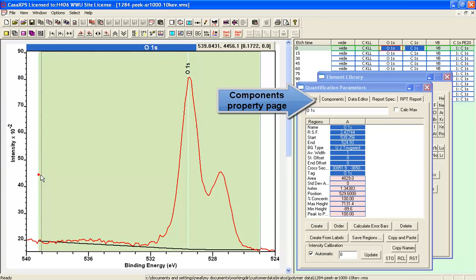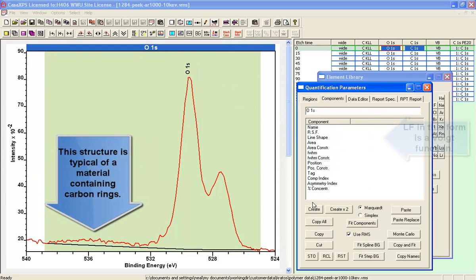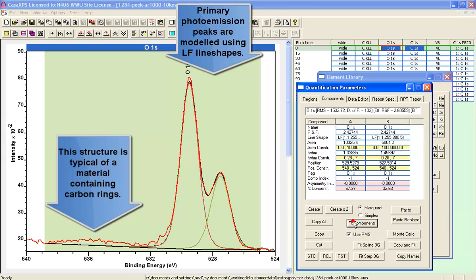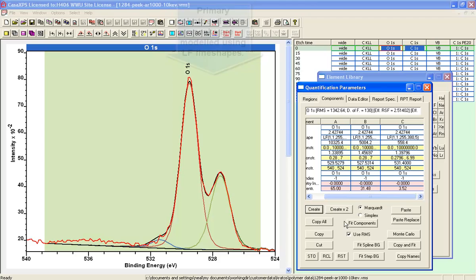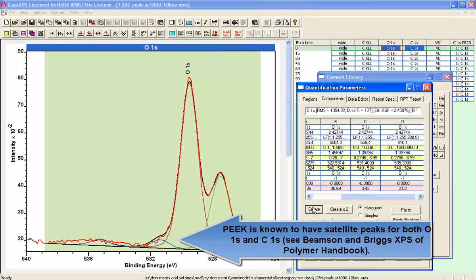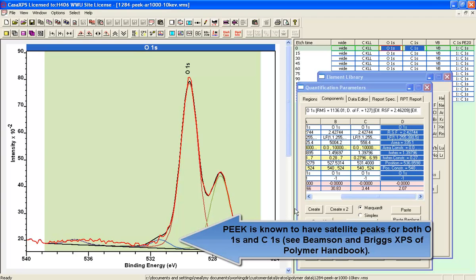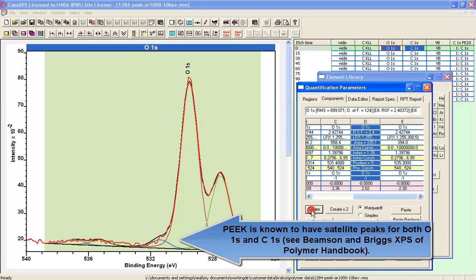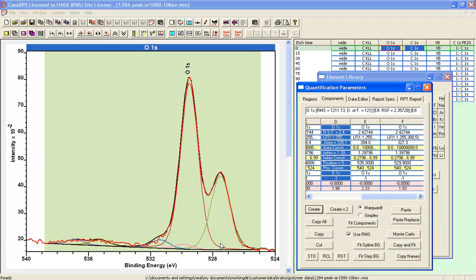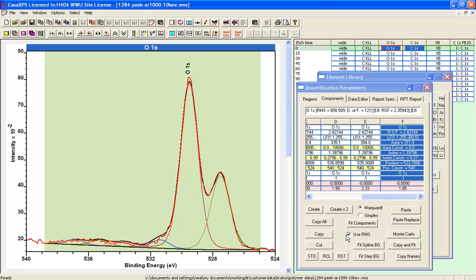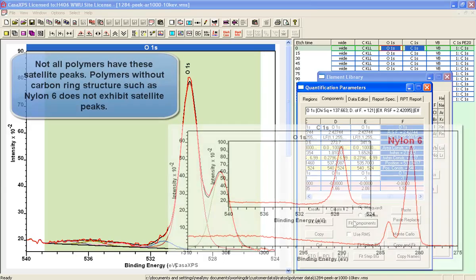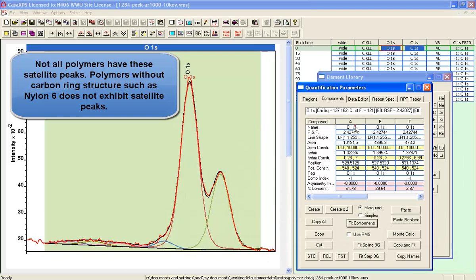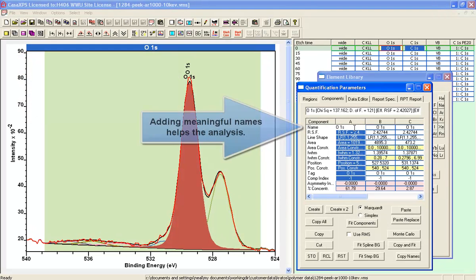Having decided that our data looks like we're free from artifacts, we can now construct a peak model and try and assess the chemical shifts that are associated with what you would see in PEEK, namely a single bonded oxygen and a double bonded oxygen. We've created a peak model where there are two main peaks, the primary peaks from the polyether ether ketone, and there are also secondary peaks which are satellite peaks that are associated with the benzene rings.